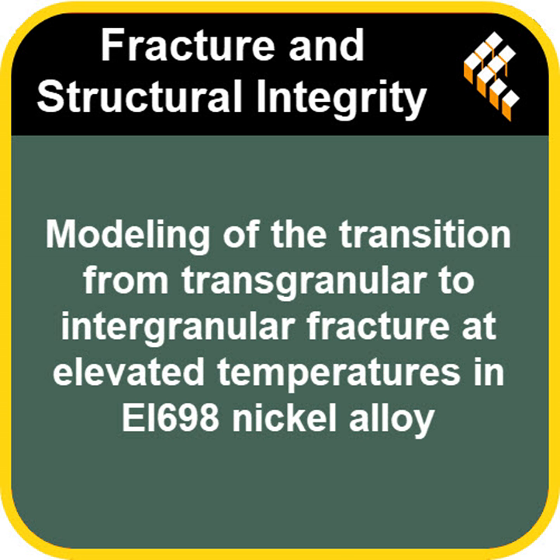Now, the paper makes some crucial modifications to the standard phase field model, which often just considers elasticity. This model expands to account for the elastic part, the plastic part, and the creep part of the total strain energy density. Much more realistic for high temperatures. And critically, the critical energy release rate, GC, that measure of the material's toughness or resistance to crack growth, is explicitly made dependent on temperature. This is absolutely key because we know temperature drastically changes how this alloy behaves. Okay, so GC isn't constant, it changes with heat. Makes sense. Right.